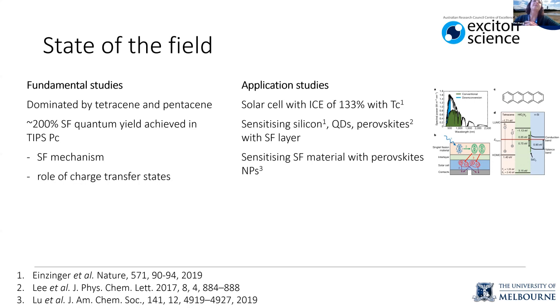And these have been good systems to study to look at the singlet fission mechanism, which is still not 100% defined. And also a lot of the fundamental studies are in dimers where you can study them in solution. So you can probe things like charge transfer states because they will be dependent on solvent. So the dielectric environment can change how those states form.